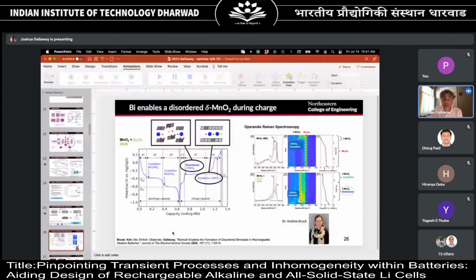So we had a Raman spectrometer. And so we put the bismuth additive in and also took it out. And as we charged up the batteries, we saw a big difference between whether the bismuth additive was there or not. This is a charge without the bismuth additive. And if we're going from bottom to top of the curve, we see one peak. And then a second peak forms at the very end.